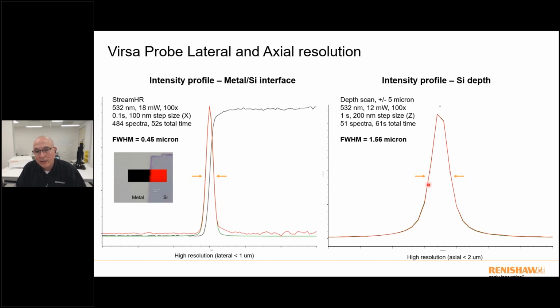In terms of depth resolution, you simply sit on top of the silicon and you drill through the Z. In this case, we did plus or minus 5 microns at 200 nanometer steps in the Z axis. And then you plot the intensity of silicon as a function of Z. In this case, we're shooting for less than 2 micron Z resolution with the ×100 optic, and I'm getting about 1.5 micron. So we're able to still retain that confocal capability with a fiber-based instrument and a portable Raman system. And this is just something that no other tool will do. So there's definitely some incredible enhancements to these type of instruments that you'll only see with the Virsa system.